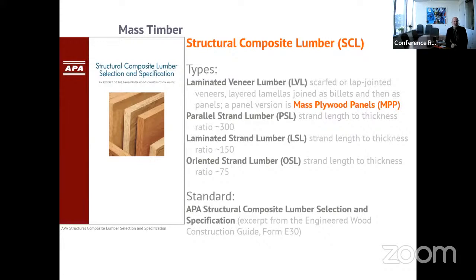The wood can be chopped into pieces that are then used as parallel strands. And the definition for a parallel strand would be that the ratio of the width to the length of the strand is about 1 to 300. A laminated strand lumber is a similar but smaller chopped element, basically a ratio of 1 to 150. And then oriented strand lumber is a ratio of 1 to 75. All of these can be married together, first laminated as fairly thin panels, and then those panels brought together to produce thicker sections for horizontal floor and roof plates, and those could be in the range of 20 to 40 centimeters even. The standards for that are the APA structural composite lumber selection specification.